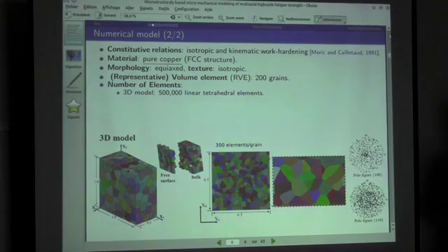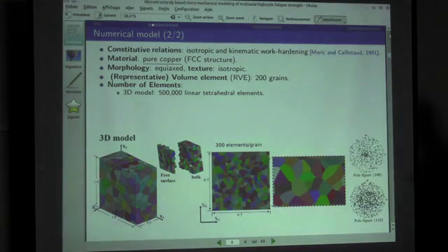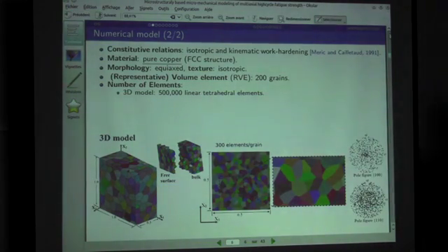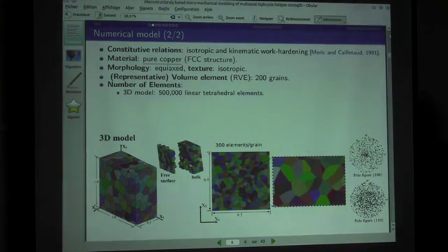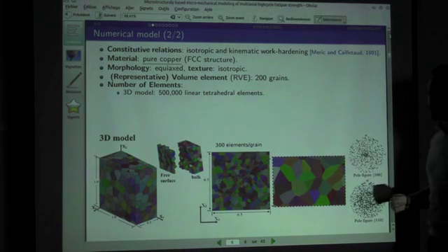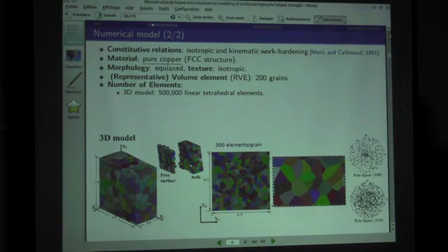So you can extract from your data the grains which are on the surface from the grains which are in the bulk, and try to evaluate the impact on the surface or the particular stress state at the surface with respect to the bulk. More or less, we are using 300 elements per grain. We have been optimizing the computations to have this figure, and that ensures a good estimate of the stress and strain at this scale without too much computation time.